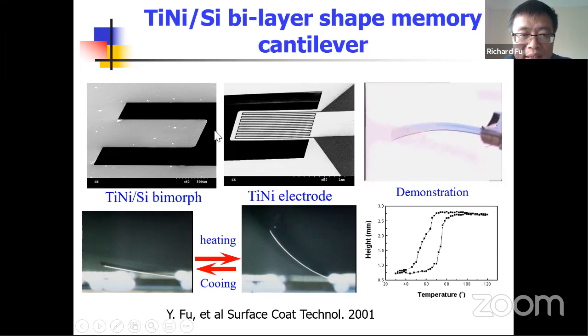So in this way we deposit the film and then pattern the titanium nickel film into an electrode, on a structure of silicon or other materials such as silicon carbide. So these are two-layer structures. Once you let an electric current flow through this electrode, there will be a heating effect.